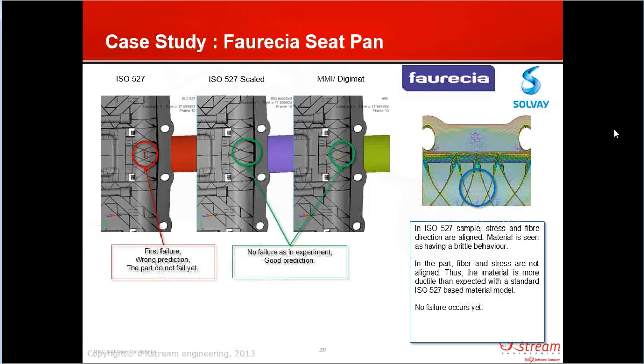And if we look at the local fiber orientations there, we can see why. In that area, you can see we've got a relatively blue color, which is telling us that the local fiber orientations are quite randomly aligned there. And that means that we're going to have a much softer material response. So this first case, where the material model is quite stiff, is not going to be able to capture that.